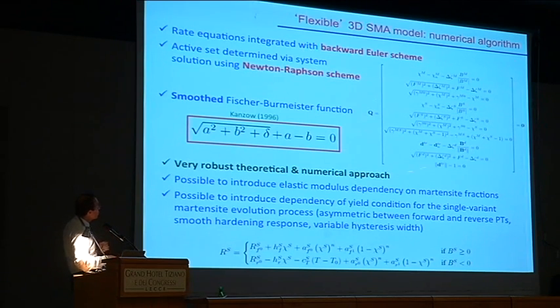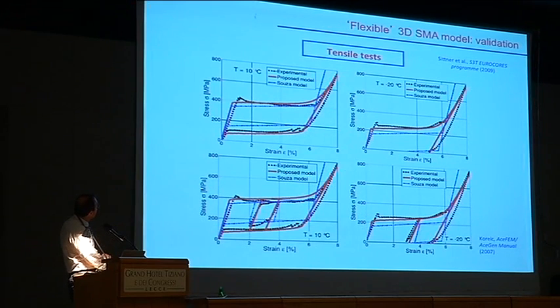And in fact, the model was performing so well that we also started to introduce more complexity, like a dependency of the elastic modulus on the martensite fraction, a smooth transition of the yield condition from the elastic to the phase transformation region, variable hysteresis width. So we really increased the complexity of the model to match the material performance, and we still use the same numerical scheme. But let's start to see some numerical examples.